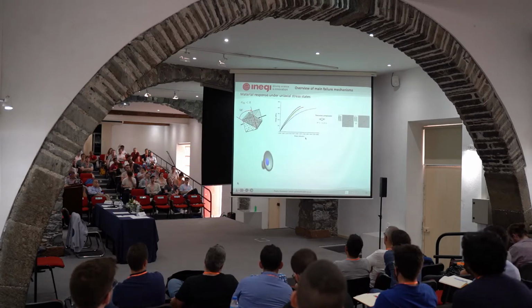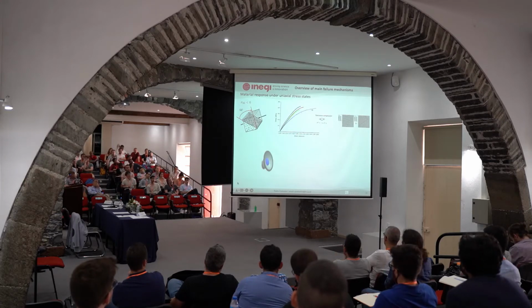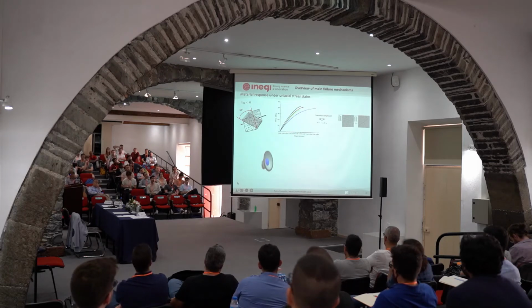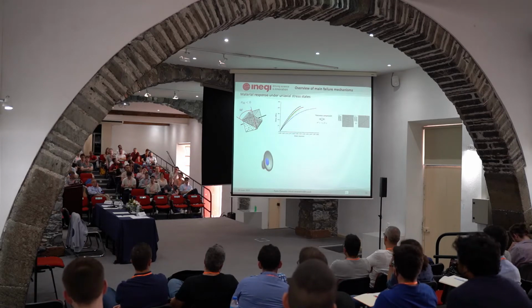Now, if you apply transverse compression, you do get a plastic response up to failure, and this fracture plane is not at 45 degrees, which means that it's not maximum shear stress that is creating this crack. Okay, so what we do in collaboration with Thomas Carter.